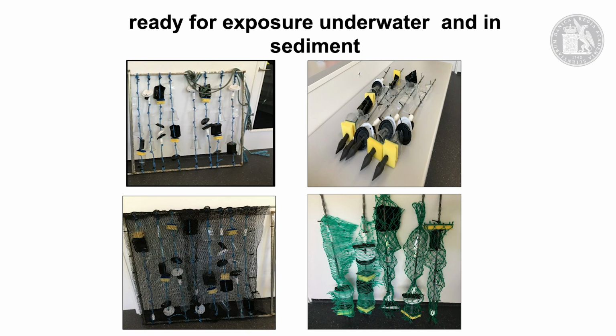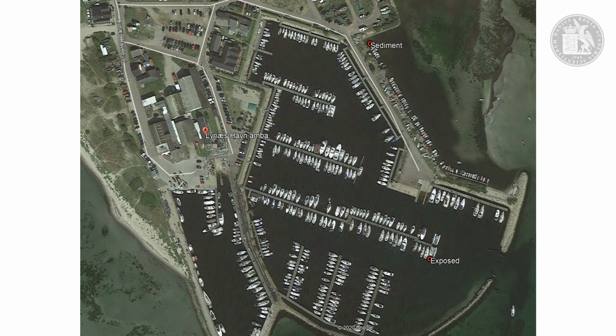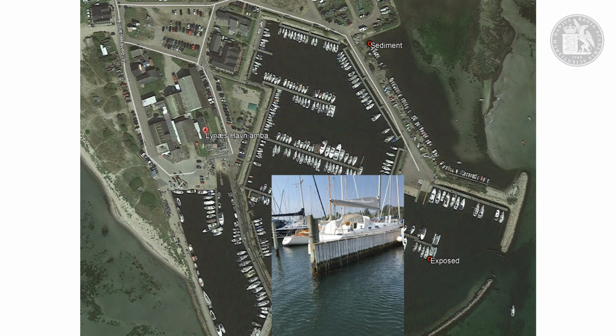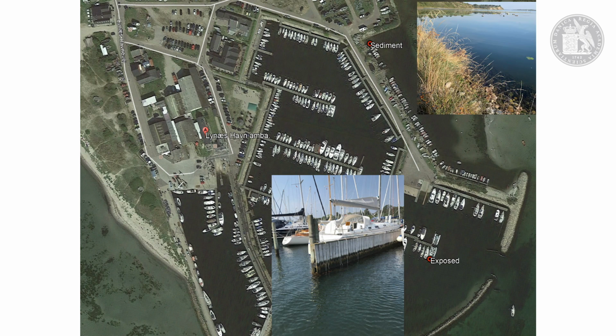We've threaded the samples on ropes and put them on a frame and put those under the water. Of course, we protected them with some net because if they should degrade to microplastics, we don't want to pollute the surrounding waters. And then we've made this kebab with different plastics on it and shot it down into the sediment. That wasn't easy, as David tells me. But here they've been under the water. The frames have been under the water here, and the samples have been put in the sediment here.